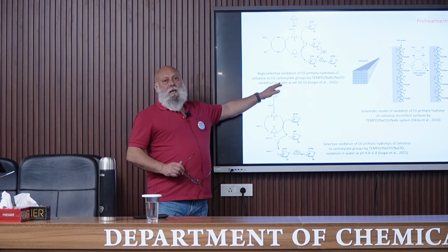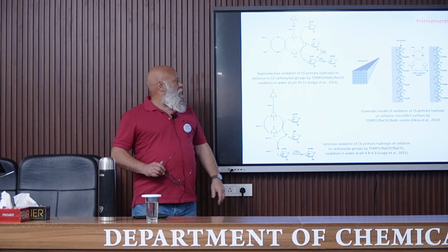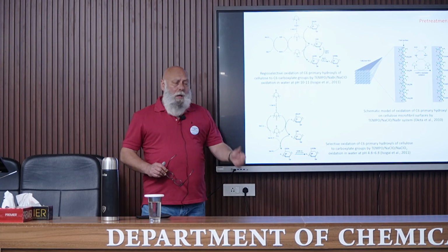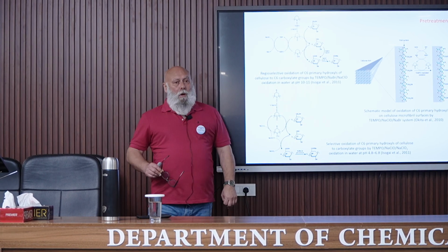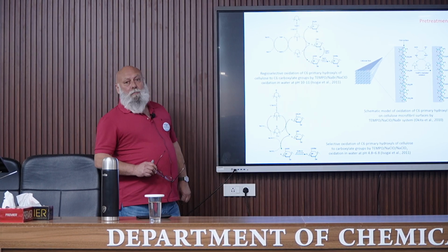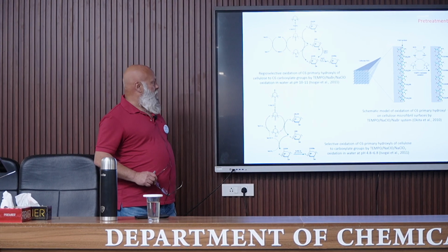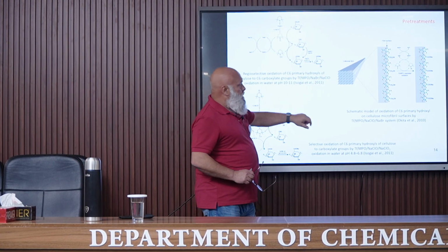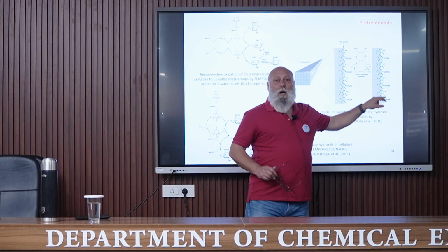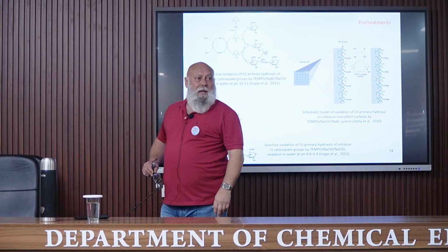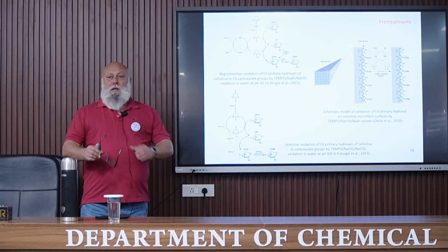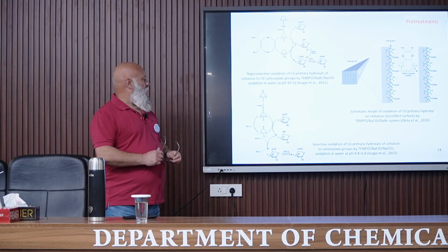In this case, as you probably know, the C6 hydroxyls are the most reactive, so they are converted into carboxylate groups, which are here, and which are negatively charged, meaning that the release of the fibrils is easier.